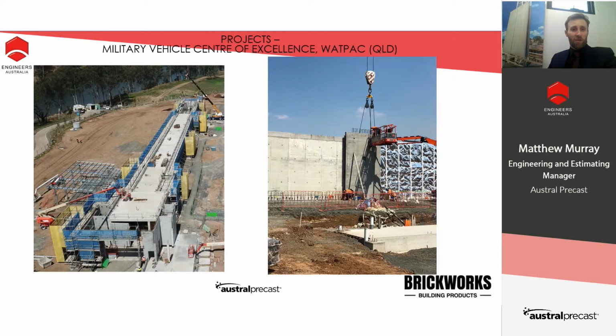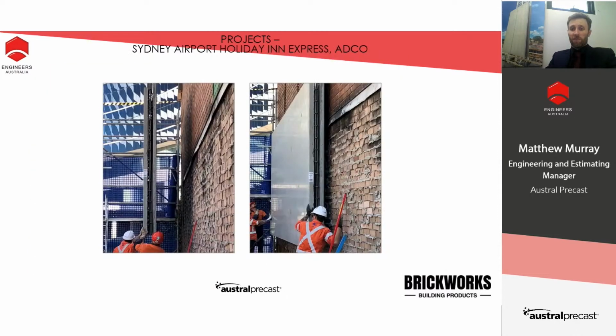The reason for this is that there is a military vehicle made on site, which is then tested. So the tank itself, the cannon must be fired prior to delivery to the Australian Defence Forces. And the reason for the use of double wall here was the fact that we could reduce the spacing of the panels to the rear of the existing tunnel, and also with that achieve both the acoustic and structural requirements for it. Speed of construction.